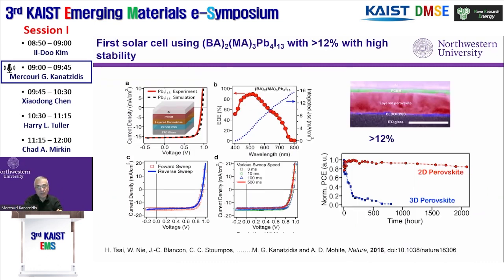So we got together with Aditya Mohite at Rice University and demonstrated that very stable solar cells could be made with 12% efficiency, which at the time was a very remarkable result because the efficiency of the 3Ds was close to 16–17% in 2016. And although this was not as good, it was definitely over 11% with no hysteresis. And this plot here in the lower right caught the attention of the community. And this is the stability plot.